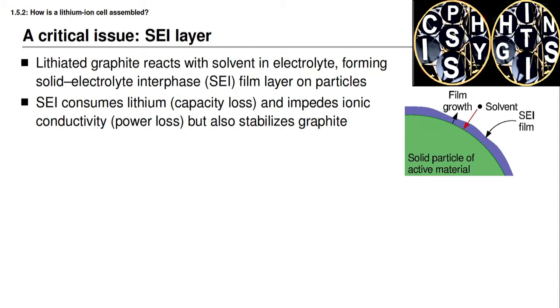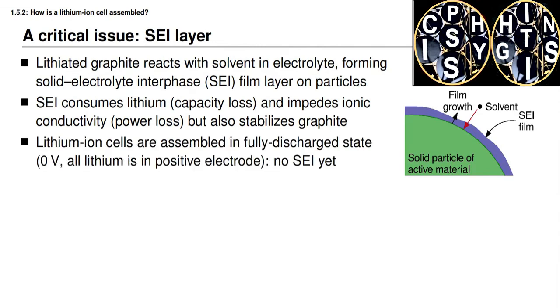The film also impedes ions, lithium ions, that want to travel from the electrolyte into the electrode and vice versa, which results in a higher resistance for this cell and therefore results in a power loss. And neither of these is desirable. But on the other hand, this SEI layer also turns out to stabilize the graphite against further reaction with the solvent, which is a positive feature. So it tends to be a self-limiting reaction.